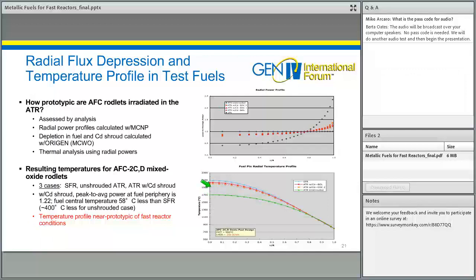And so while we haven't achieved a prototypic neutron spectrum inside the test articles, what we have achieved is a near prototypic temperature profile. And so for those fuel performance processes that are primarily driven by temperature and temperature profile effects, we should be capturing those pretty well.